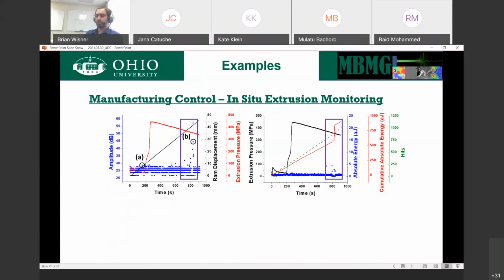We're extruding aluminum wire. The intention behind doing this particular process is we're trying to improve the conductivity of that particular wire. So what you see here is the extrusion pressure in red, the ram displacement in black, and the acoustic emission in blue. On the right-hand side, we also have acoustic emission activity in red and green, just to give you a couple of different ways of seeing what's happening.